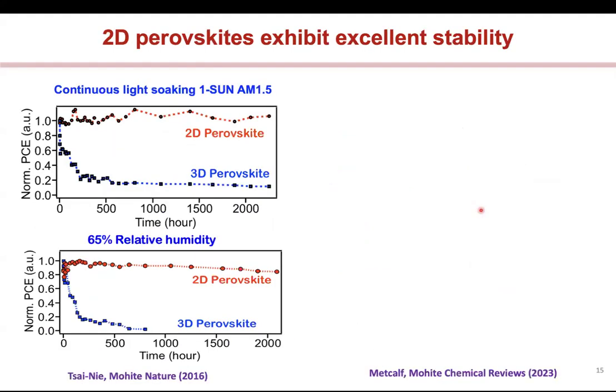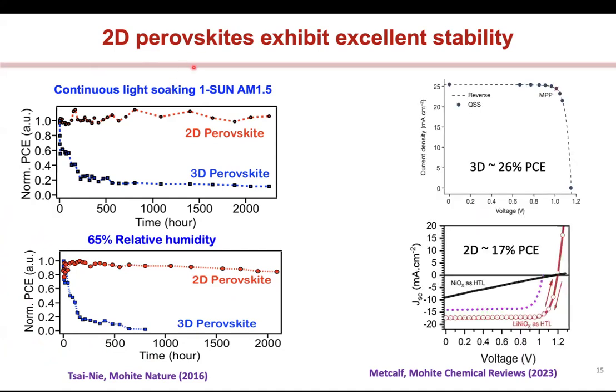And so, we started working on this material really early on. And this was really a seminal paper. It's back from 2016, during my days in Los Alamos. And we showed that, in fact, by tuning the 2D perovskite somewhat, you can make an efficient solar cell. You can make something which is about 17% or something like this, or at that time it was 12. But most importantly, what you can get is really good stability compared to the 3D perovskite.